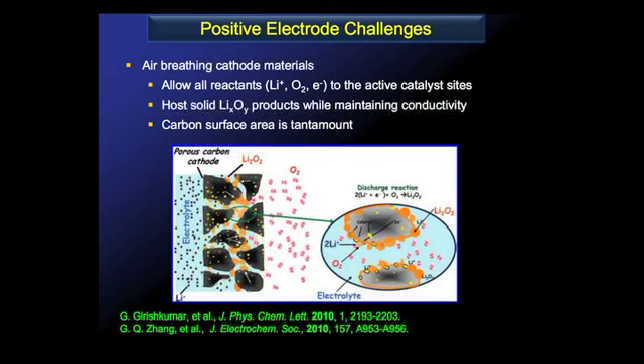Just like in the sulfur case, you need a porous carbon, in this case to host the Li2O2, which is the reduction product. This has to allow all of the reactants to reach the active catalyst sites. Catalyst, you say, what's that for? Well, it turns out that oxygen, unlike the sulfur system, which cheerfully reduces and oxidizes, needs a catalyst, both for oxygen reduction and oxygen evolution. And especially for oxygen evolution, this is an issue. So the porous carbon system has to host the products. It has to maintain electronic conductivity. It is the worst aspect of the fuel cell because you need a triple phase boundary, and the carbon surface area is particularly important. And this has been studied by a host of people over the last couple of years.